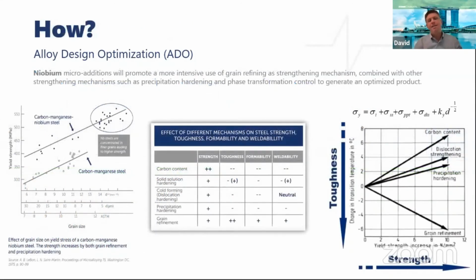And as I said, the idea with niobium is to rebalance the strengthening mechanisms. Usually what we do is reduce the amount of strength coming from solid solution strengthening and precipitation hardening, and increase the grain refinement and grain size homogeneity effects on the mechanical properties. By doing that, we usually achieve improved or equivalent mechanical properties, and it allows us to play with the addition of other elements such as carbon, manganese, vanadium, nickel, titanium, and several other elements.